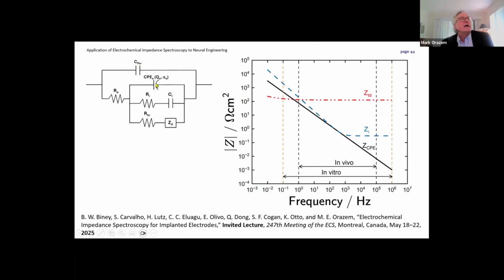Here we have, this is from our in vitro data. This is basically a CPE that corresponds to the flat surface or the charging current on the electrode surface. This part here is associated with the iridium oxidation and reduction, and this part here is associated with oxygen reduction. We have a kinetic term here, and we have a diffusion term over here.